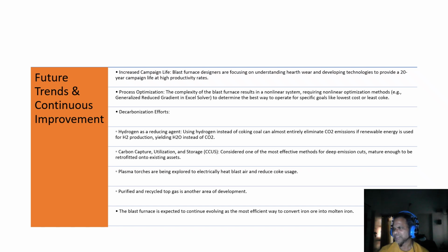Decarbonization effort, this is a major area of focus. One promising avenue is the use of hydrogen as a reducing agent. Replacing coking coal with hydrogen can almost entirely eliminate CO2 emission from the blast furnace, producing water instead of CO2, especially if hydrogen is produced using renewable energy. This is a significant step towards green steel. Carbon capture, utilization, and storage is considered to be one of the most effective methods for deep emission cuts. The technology is mature and can be retrofitted onto existing assets, allowing a steelmaker to maintain their current production infrastructure.